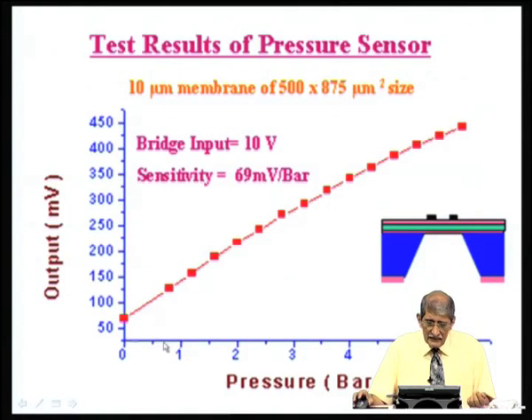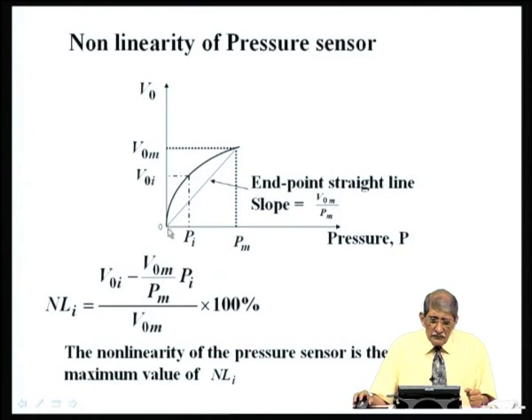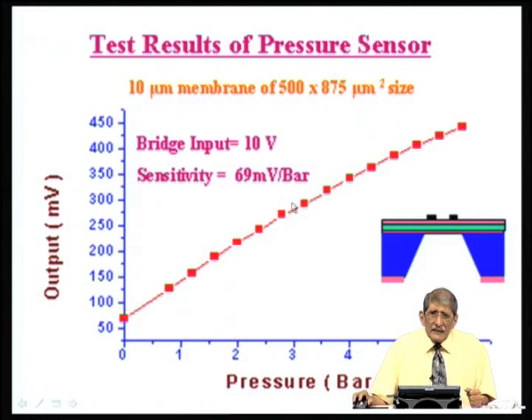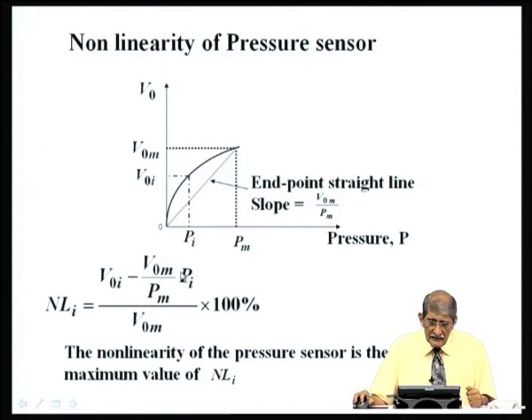But if you want to use it without considering the non-linearity, you can use it. If you want a linear range of pressure, you must restrict it to about 3 bar. Where it is linear, you get about 69 millivolts per bar for 10 volt input. For 1 volt input, it is about 6.9 millivolts. Okay. So, there is a term called non-linearity which is defined. The non-linearity can be seen like this.